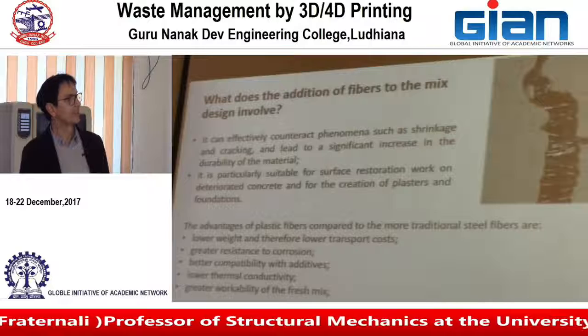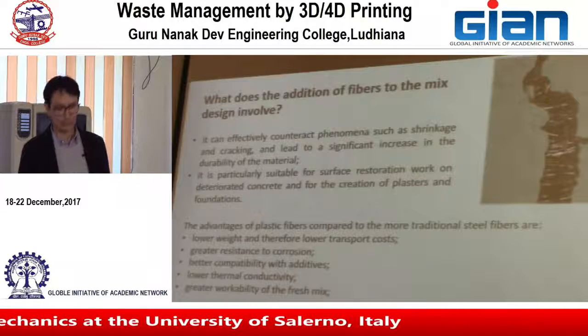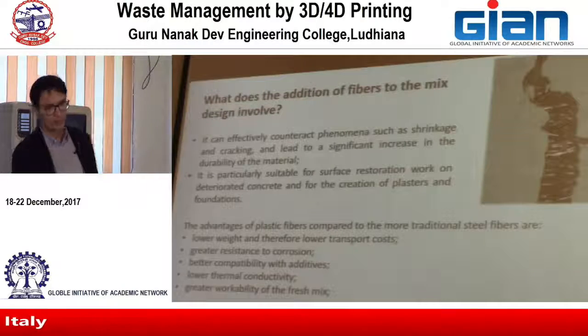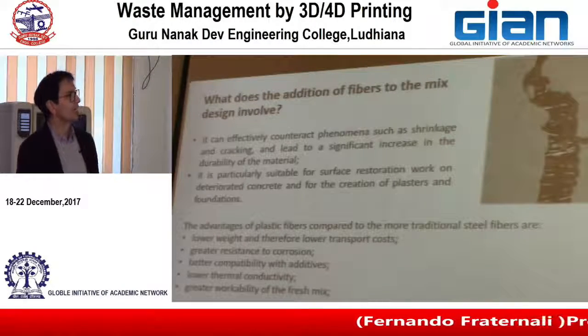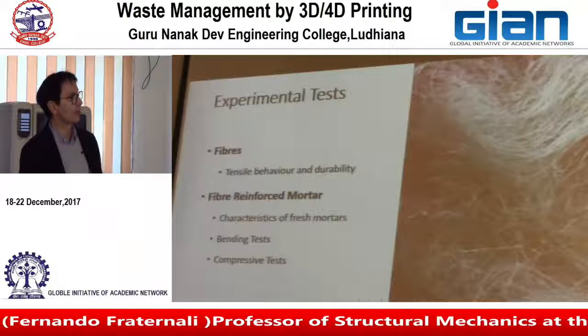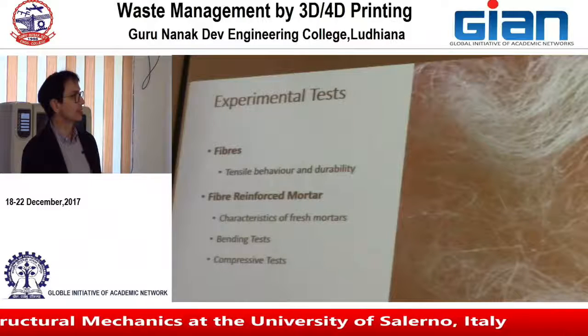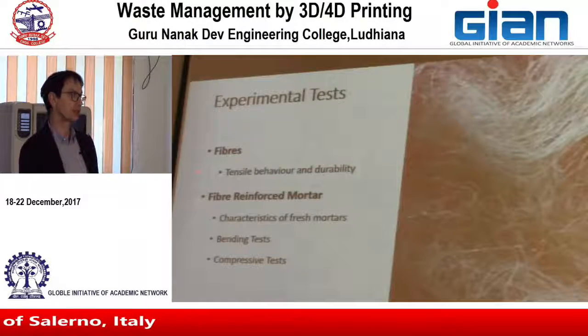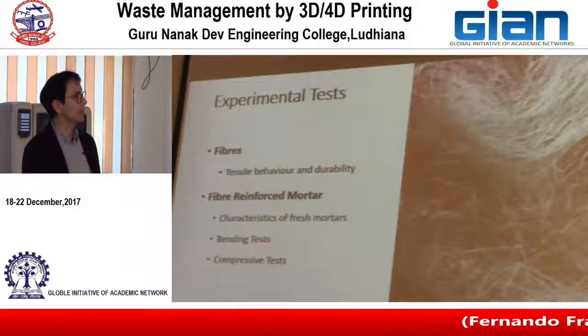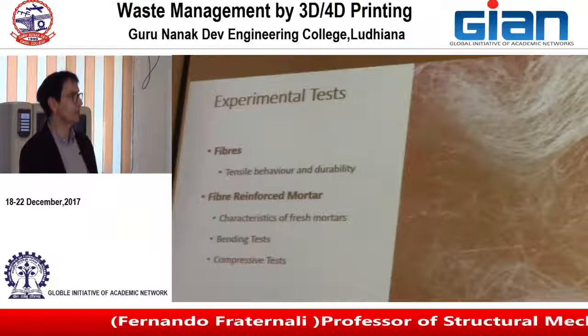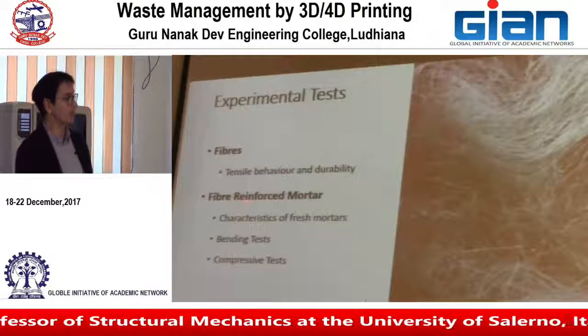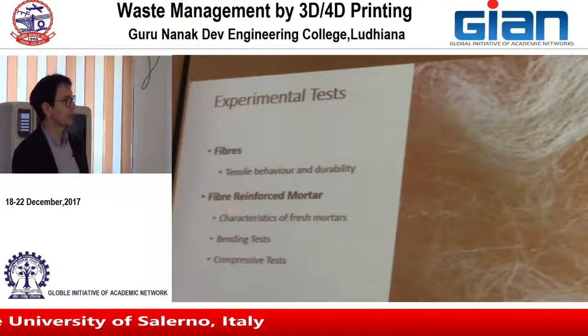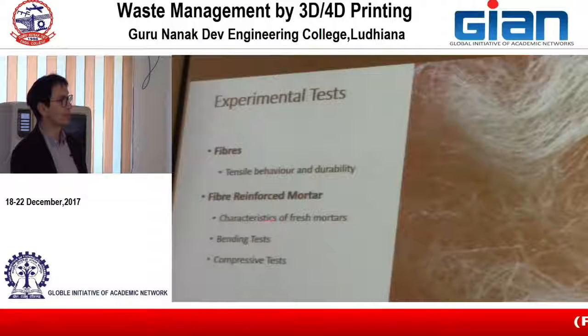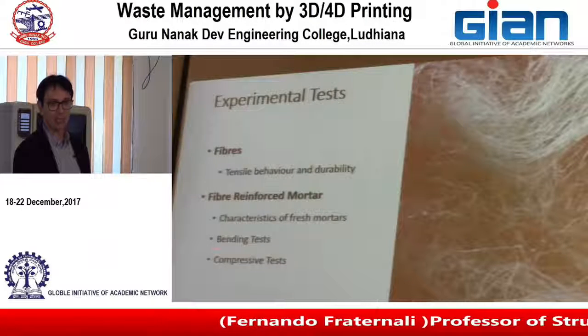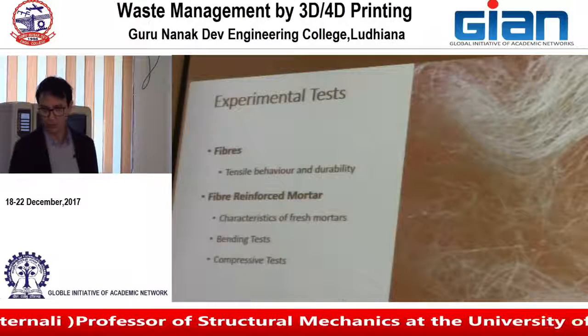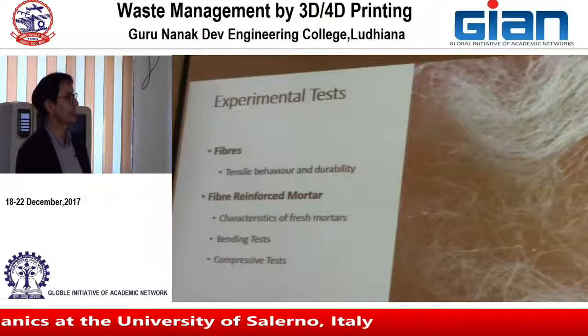So I don't want to repeat these considerations about the positive effects of adding fibers to cementitious materials. And which were the tests that we carried out? We conducted the studies on the fibers and on the fiber reinforced mortar. On the fibers, we tested the tensile behavior and durability. And for the mortar reinforced through recycled nylon fibers, we performed bending tests. We also conducted some slump tests to show workability, and then bending tests and compression tests.